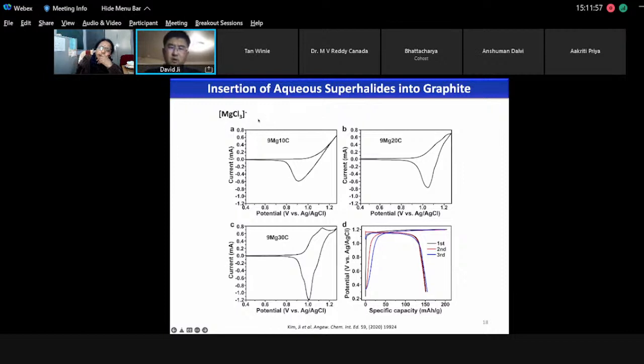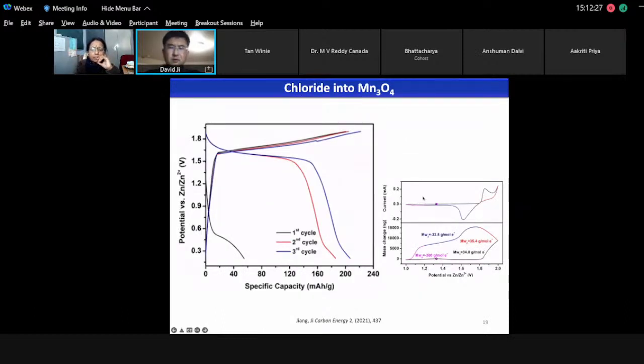And when this superhalide is formed and getting concentrated, the insertion potential will go down for its insertion in graphite. And also when the electrolyte is concentrated, water will be less subject to oxidation reaction, or water oxygen evolution reaction, OER. So we do have some charge discharge behavior for this ion storage in graphite, although the Coulombic efficiency is not that good. All right, we have another chloride insertion.